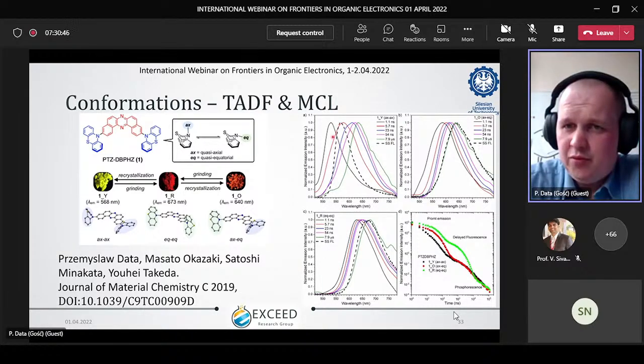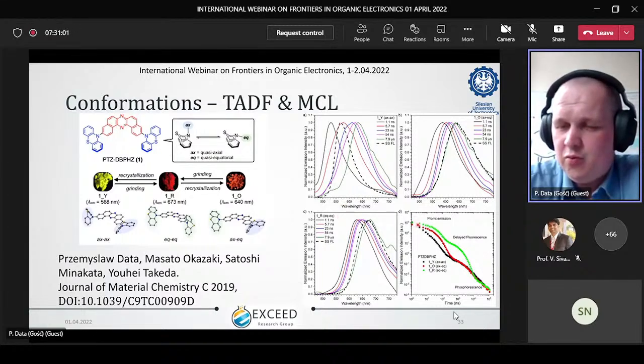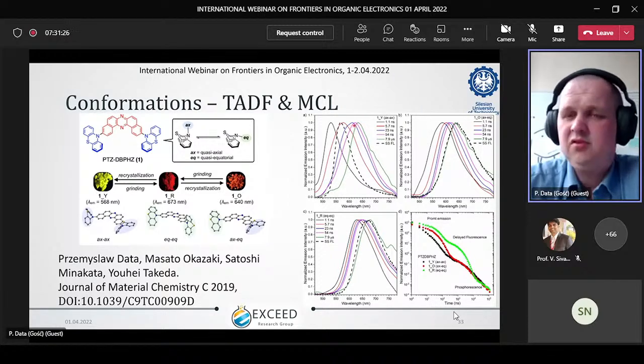And here is an example. Here I analyzed different pure crystals, because we need to know how our emission behaves for different conformers. We had three different conformations: axial, equatorial, and axial-equatorial, and we analyzed how the emission changes over time, how the prompt emission and delayed fluorescence look. We observe that in the case of the equatorial we have pure TADF emission, and usually the ST gap is much smaller, whereas in the axial we observe mostly room temperature phosphorescence, a very efficient phosphorescence process at room temperature.